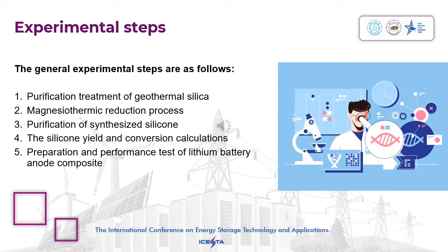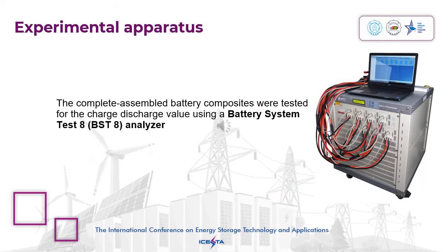Generally, the experimental steps are as follows. First, purification treatment of geothermal silica, magnesiothermic reduction process, purification of synthesized silicon, silicon yield and conversion calculation, and preparation and performance test of lithium battery anode composite. The completely assembled battery composites were tested for charge-discharge value using a BST-8 battery system test analyzer.